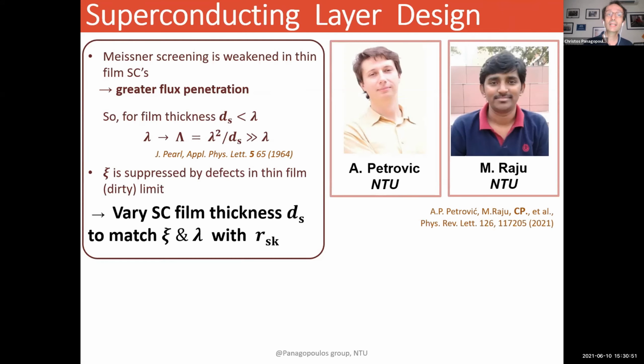they work. Now you have to understand when you develop this superconducting layer is that the Meissner screening becomes weaker in thin film superconductors. And therefore you have greater flux penetration. So if you have a film which, let's say its thickness is ds and it's smaller than the magnetic penetration depth in the superconductor, then you have to replace the magnetic penetration depth with a Pearl length, which is capital Greek lambda.